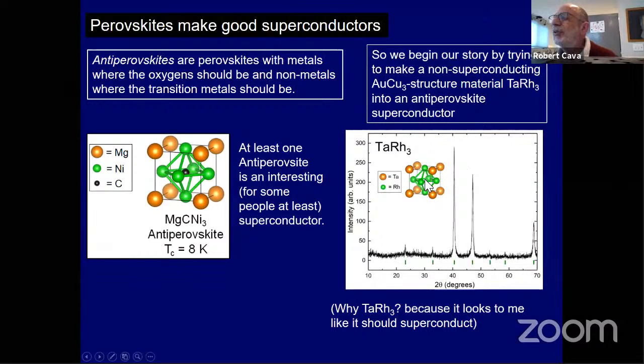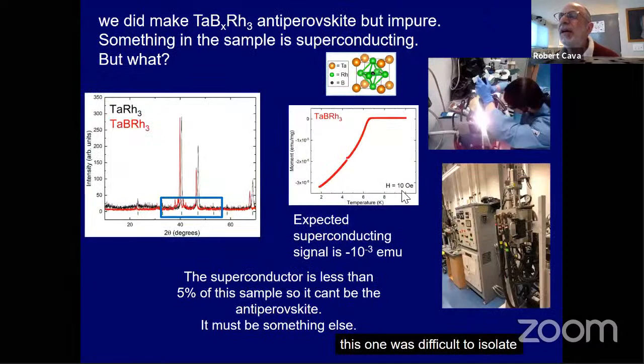So we tried to put boron in this hole to make a superconductor out of tantalum, rhodium-3. And sure enough, boron went in the hole and it made a superconductor. Oh my God, so it worked. No, it didn't quite work because the superconducting signal was 2 orders of magnitude too small. So something was superconducting in this sample, but not the main phase. Even though the boron went in there to make tantalum, boron, rhodium-3, like magnesium, carbon, nickel 3, it's these little peaks in the pattern that are very hard to get anybody to pay attention to, that were the superconductor. That's very annoying, but there it was.